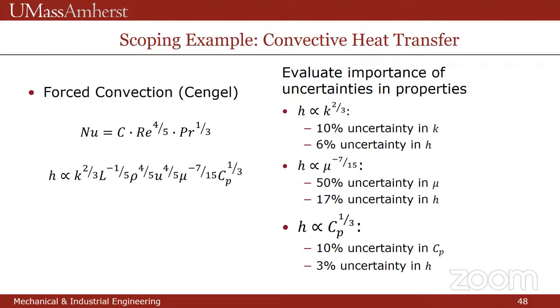With viscosity, the dependence is smaller, which is good, because it's really hard to get viscosity that's repeatable better than about 25%. When they do round robin studies, sending samples of the same heat of metal or of slag to different laboratories, typically 25 to 50% variation is what they measure, and so on. So here, with 20 minutes work, you can decide how important these different inputs are and which things you should spend $100 or $100,000 measuring more precisely, and which things you can say, well, metals have a conductivity of about 100 watts per meter K, done. Oops.